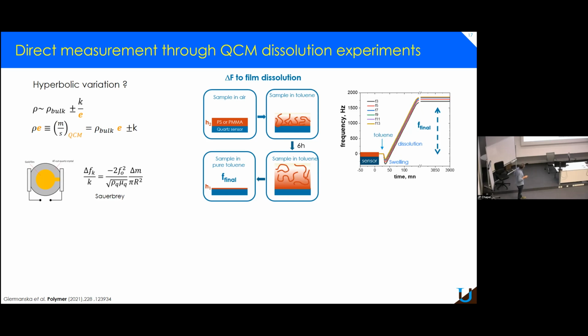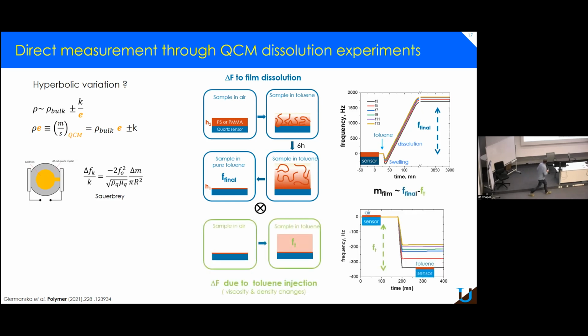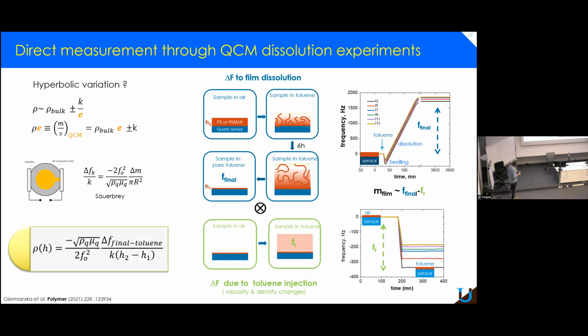So you have toluene, so you have a decrease in the frequency. This is typically due to the swelling. And after a couple of minutes, you see the dissolution of the film. And at the end, it's constant. You don't have anything anymore on the surface. So you have obviously to take into account, well, it's not a big deal, the fact that when you enter toluene into the QCM setup, you go from air to toluene, and going from air to toluene, the density of the liquid medium is changing, the viscosity is changing, and so you also have a drop in the frequency. But if you combine both, actually at the end, you could access directly from those experiments the density variation in thin films directly.